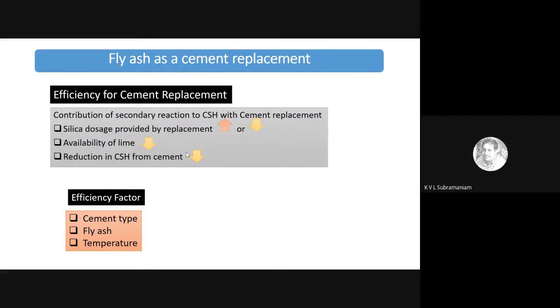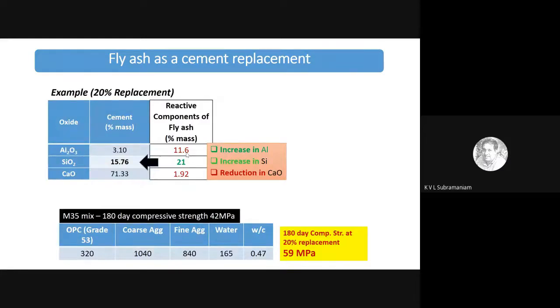So net, I have to figure out what is the total gain and what is the total loss. And for characterizing that, we have developed... look at these numbers. Suppose I look at 20% replacement, and I'm giving you a numerical example. If you look at cement, which is shown in the table on the top, cement contains 3% alumina, 15.76% silica, and about 71% of calcium.